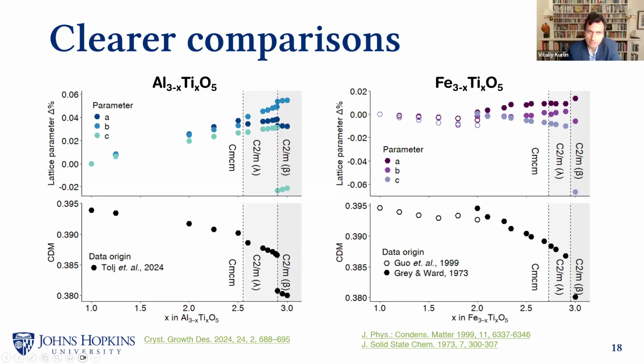Shannon, this apparent discontinuity of the CDM at about 2.9 when x in this picture, how does it correspond to the continuous graph that was shown earlier? So the lattice parameters do change discontinuously here. So the continuous transition means that we're looking at the phase changing as we're adding more titanium here, but it is a discontinuous phase transition in that the lattice parameters change abruptly.